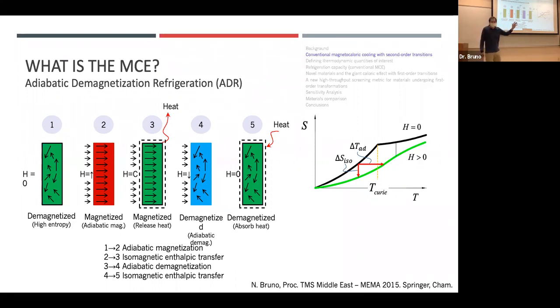What we could do is apply a magnetic field to the material, and it aligns all of our magnetization vectors, and that decreases our disorder. It decreases our entropy. If we apply that magnetic field in insulated conditions, we actually will heat the material up. Well, if we can remove that heat and then decrease the magnetic field really quickly, we can generate this adiabatic demagnetization refrigeration type system. Essentially, it absorbs energy to randomly orient those magnetization vectors again. Then with this cold material placed at some control volume, we can absorb energy to heat it back up, and then we can repeat the process and use it as a heat pump.